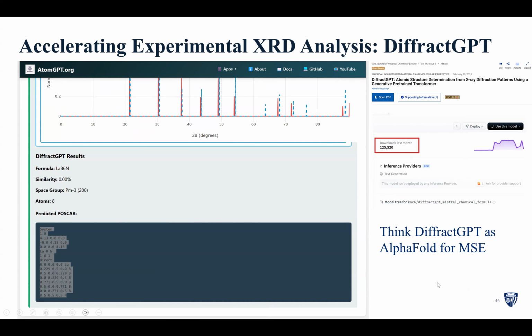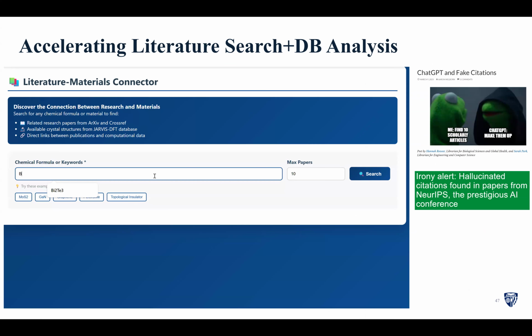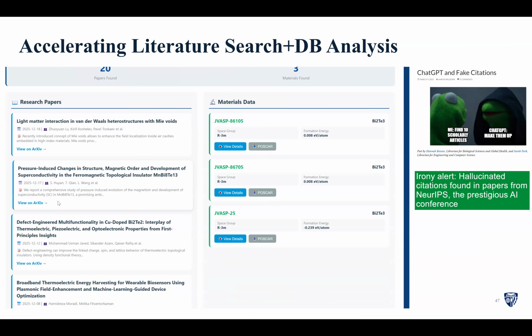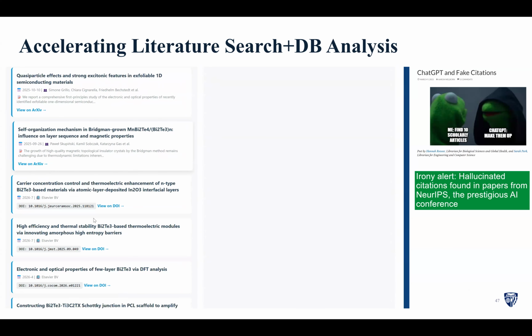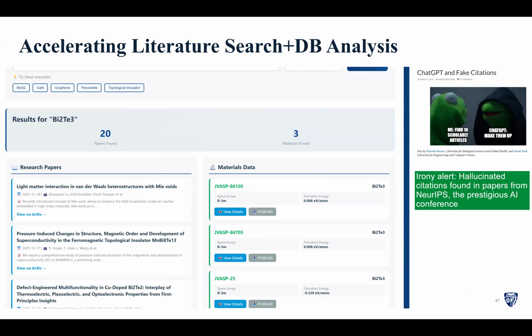It's also available, as I said, in an API format. We can also use the AtomGPT API to search for materials and search literature at the same time. Suppose in this instance, we are seeing how ChatGPT and other LLM models can hallucinate and make fake citations. Wouldn't it be nice to add, in an agentic way, features such as arXiv and Crossref to reduce this hallucination? In fact, at the recent NeurIPS, hallucinated citations were found in papers from NeurIPS, the prestigious AI conference. So this is a major challenge, and one of the ways we can solve it, especially for materials: if you search for bismuth telluride in this particular app, you'll get papers from arXiv which are authentic, and also get comparison from the JARVIS-DFT database, so you can do one-to-one comparison.